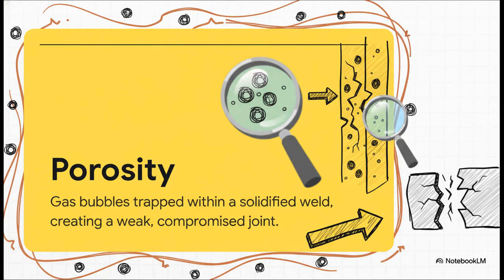But because the metal is freezing so fast, those little hydrogen bubbles get trapped. This is called porosity, and it creates all these tiny voids and pockets all through the weld, which just kills its strength and integrity. It's a hidden defect that can lead to a total catastrophic failure down the line.